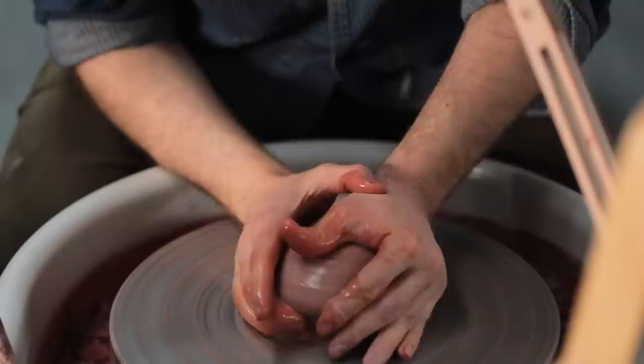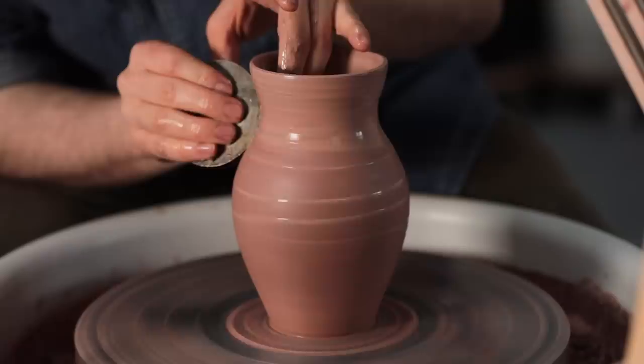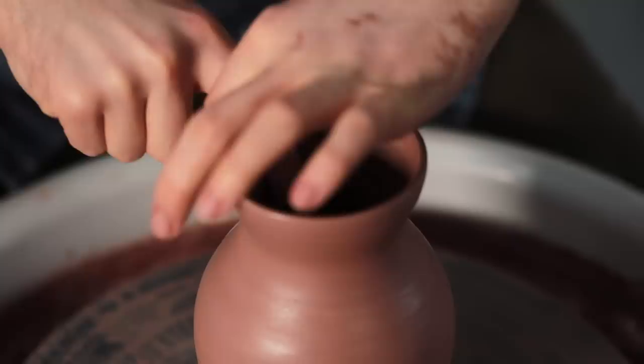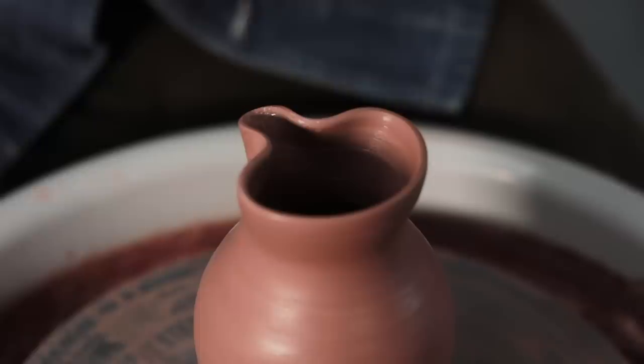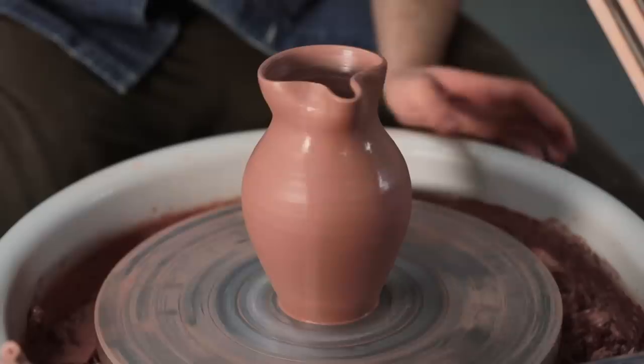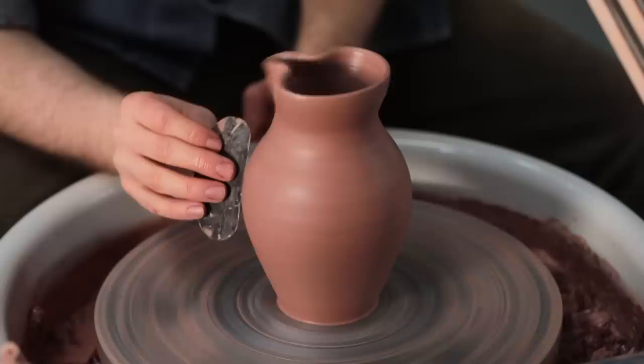There is another style of spout, and it's one you often see in British country pottery, such as those made by Michael Cardew at Wenford Bridge Pottery, and by Sven Beyer. In 2013, I did a masterclass with Sven where I learnt to make these. Instead of being a lip that's pulled, the spout is really bent into place, with a rim that's left relatively thick, and despite that, it pours wonderfully. The neck is collared in, and then the top is thrown with a very gentle outward curve that concludes almost vertically. The lip is then simply folded almost into this shape, with a very pronounced spout and sides that are really pushed in. It's either side where the walls are angled inward that really directs the flow of liquid and prevents it from gushing over the sides. This style of spout requires no stretching or thinning of the rim, which means in some ways it can be easier to create, yet it relies on a very specific thrown shape to work.